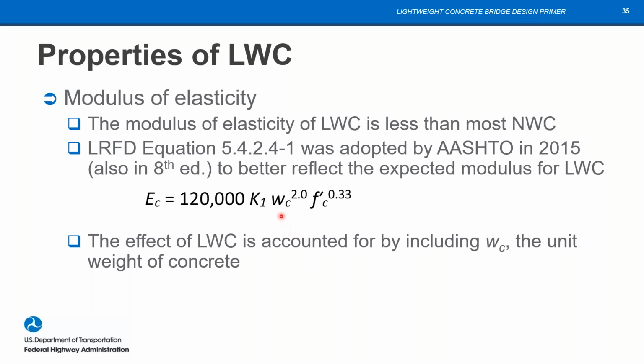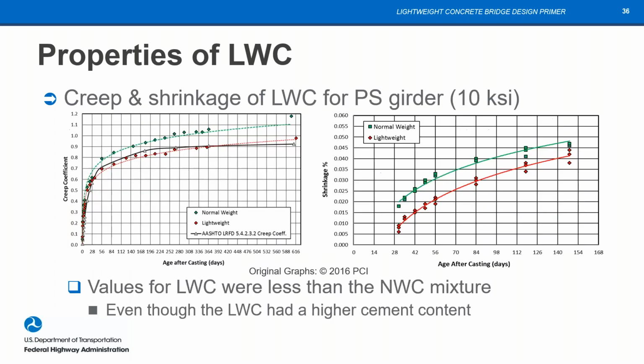And we have the unit weight that's in there, as it has been for many years, but in a different equation now. This is an interesting set of data coming from pre-stressed girders up in Washington State, where you're looking at creep on the left and shrinkage on the right. The red lines are for lightweight concrete, the green lines are for normal weight concrete, and you see that in both cases the creep for lightweight is less than the creep for normal weight, and on the right the lightweight concrete is less than the normal weight as far as shrinkage.